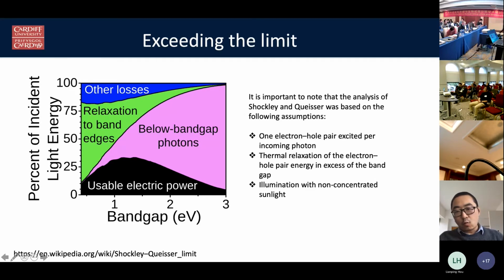The first is about one electron and hole pair excited per incoming photon, which means you have one photon, you can only excite one pair of electron holes. The second thing is the thermal relaxation of the electron hole pairs, because if you have very high energy photons, the energy above the band gap will be dissipated as thermal heat.